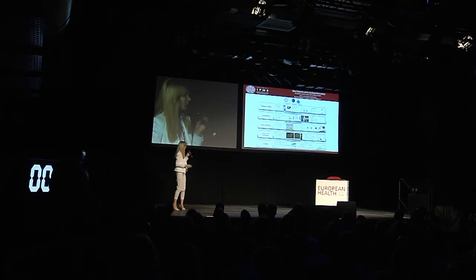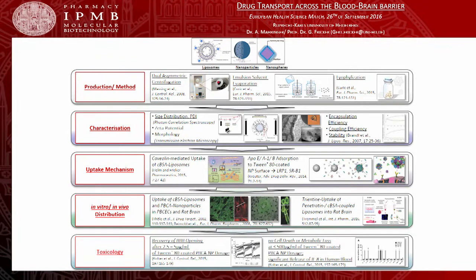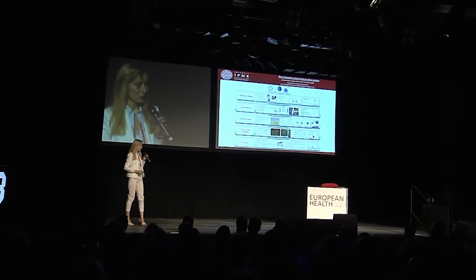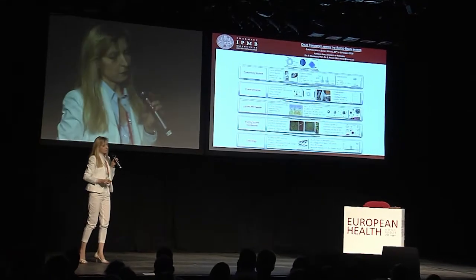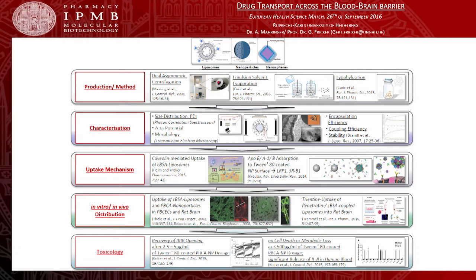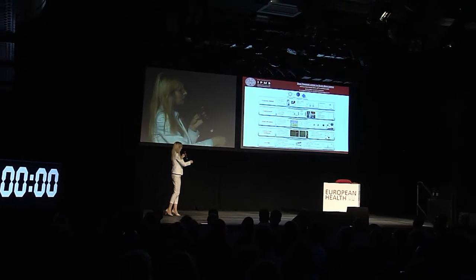We have been able to show that once liposomes are produced via a dual asymmetric centrifugation method, or that polybutylcyanoacrylate nanoparticles are produced via a solvent evaporation method, and after their zeta potential and narrow particle size distribution had been determined, cationized liposomes and surface-coated nanoparticles are taken up either via an absorptive or receptor-mediated transcytotic mechanism. We have achieved a 3 to 16-fold accumulation in the brain compared to a single drug solution after intravenous administration, without evidence for toxic or acute inflammatory effects in rats and human blood samples, due to the biodegradability of our tested materials, except for a slight, temporary and reversible opening of the blood-brain barrier.